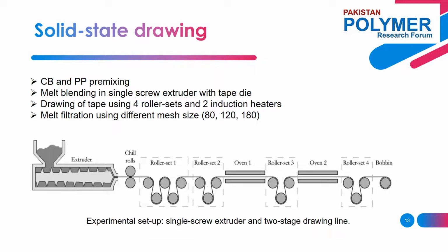Next is solid state drawing of post consumer isotactic polypropylene. In this research, 1.5 percent of carbon black and isotactic polypropylene pellets were premixed before the polymer processing step. All isotactic polypropylene grades were processed using a single screw extruder attached to a melt pump and a tape die of 15 millimeter width and 1 mm height. Melt filtration was achieved with filters of different mesh sizes ranging from 80 micrometer to 250 micrometer.